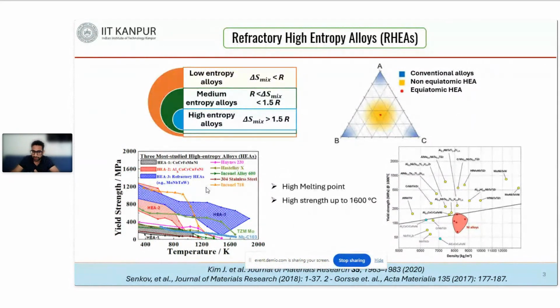One of the initially developed refractory high entropy alloys was the molybdenum niobium tantalum tungsten alloy. When it was tested, it showed very remarkable properties in the temperature range of 1200 Kelvin to 2000 Kelvin, in comparison to conventionally used high temperature alloys like Inconel 718 and Hastelloy.